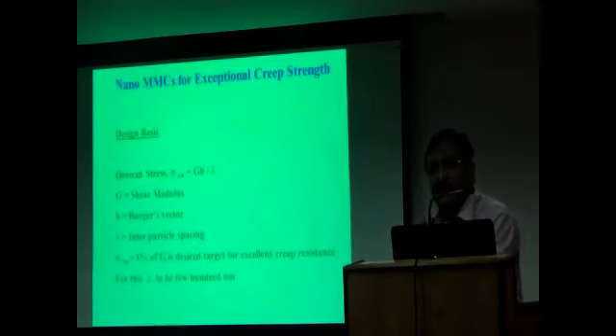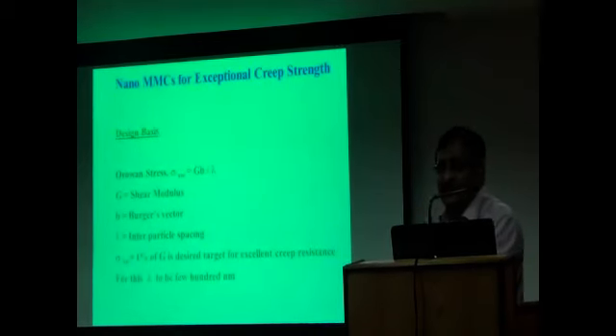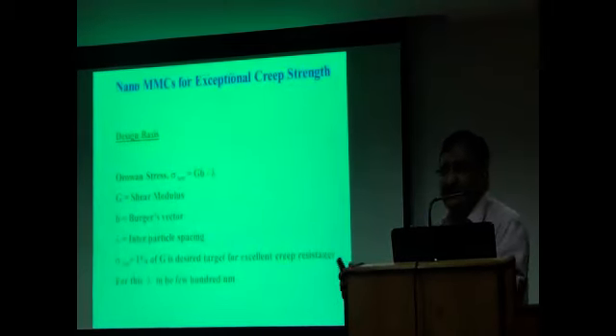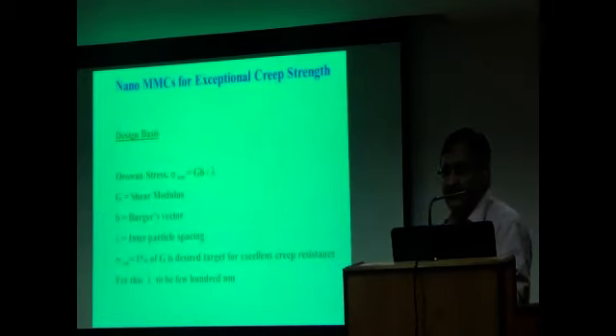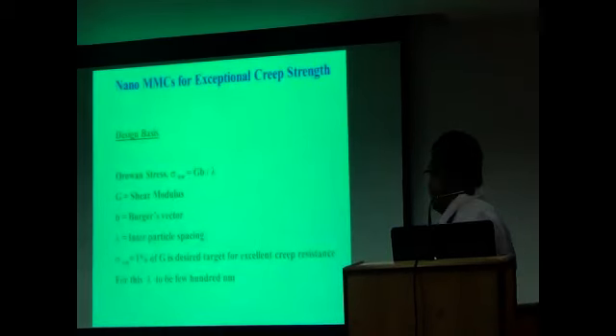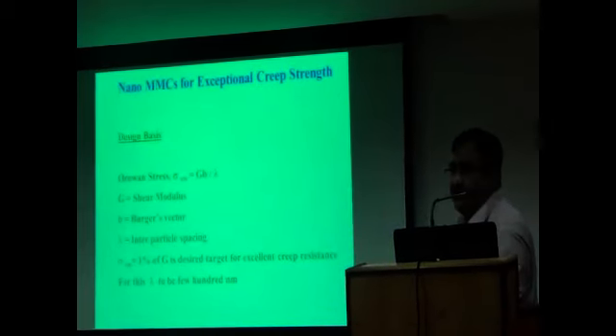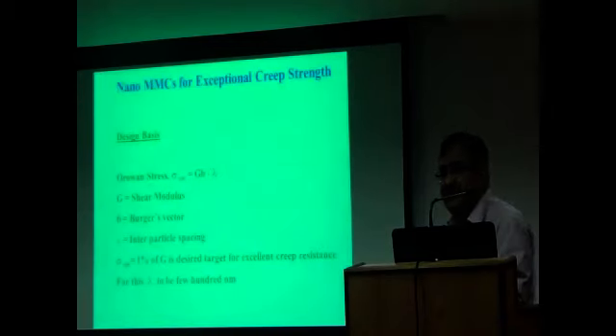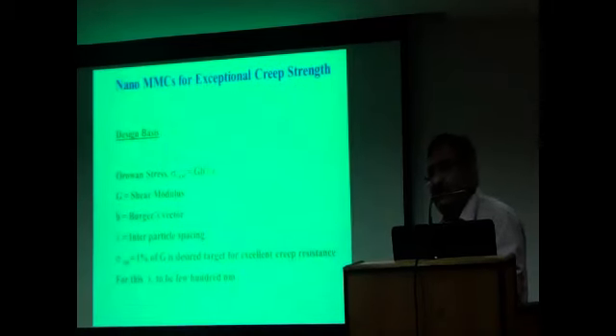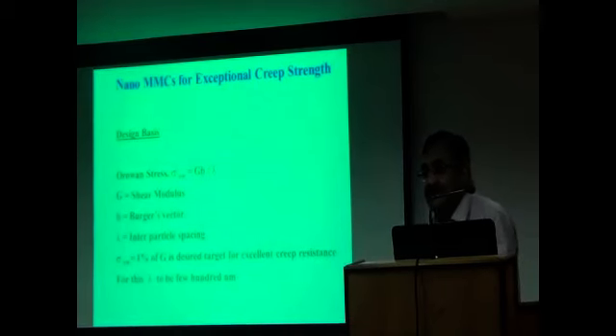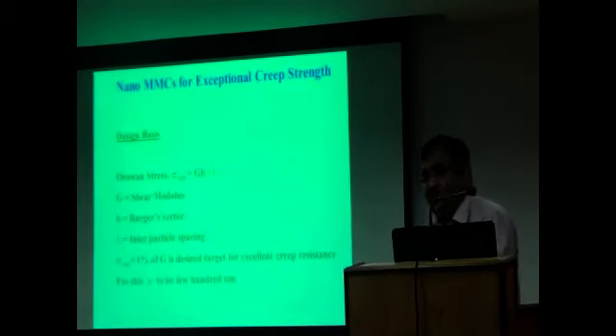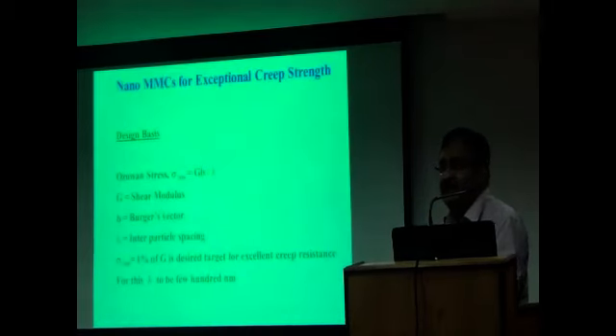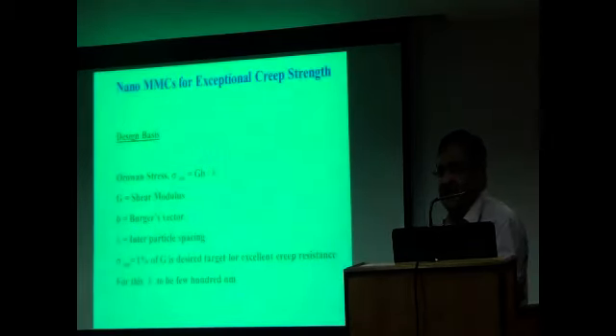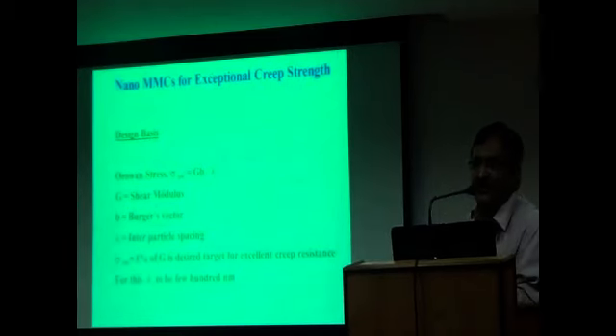If you want to really reach 1% of the shear modulus as strength, the basis for such kind of alloy design is that you will need to create an interparticle barrier for the dislocation movement, having an interparticle distance of a nanometer size, less than a few hundred nanometers. And you can achieve this few hundred nanometer interparticle distance only when you have nanoparticles as the dispersed phase. So based on that clue, that understanding, we went ahead adding nano-sized particles or creating nano-sized dispersions in aluminum magnesium alloys.